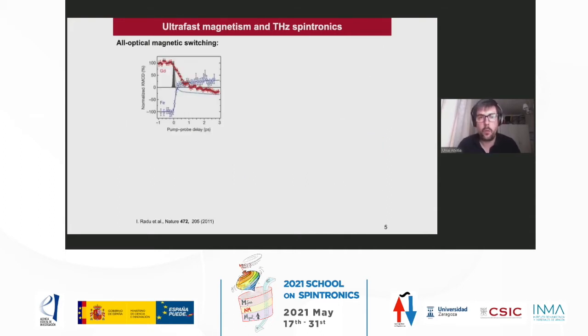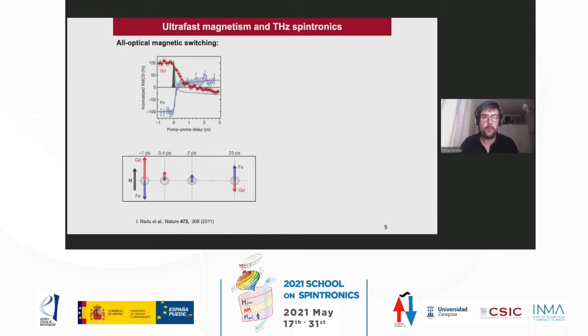This is already possible. For example, one can switch the magnetization in the picosecond time scale in specific materials, like gadolinium-iron alloys, as shown here. After applying a femtosecond laser pulse, the magnetization of iron and gadolinium reduces. Iron switches polarity and aligns parallelly to gadolinium, creating a transient ferromagnetic state that lasts for a couple of picoseconds, then gadolinium switches magnetization. So it's possible to switch magnetization in specific materials using just a laser pulse.